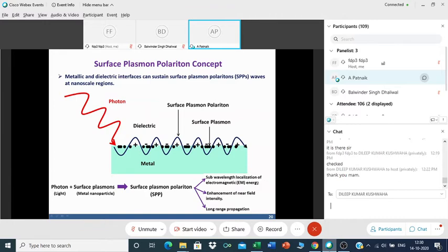It's sub-wavelength localization of electromagnetic energy. It's a localized EM wave, enhancement of near field intensity, and long range propagation. Okay, the wave or the frequency that is created because of this particular concept can propagate to a large distance. And briefly, this is what is known as surface plasmon polariton concept. And the resonance that is taking place in graphene materials is because of this SPP concept. Okay.